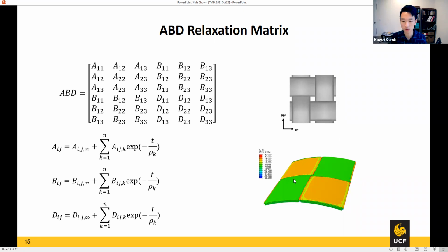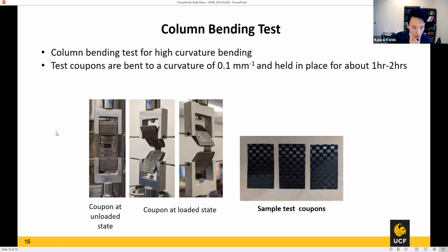So this is just a picture of what we actually have inside the simulation. This is a plain weave unit cell. There are 4 layers of thin ply composite to make up the total composite. In this particular case, we are trying to do a bending simulation to get the bending stiffness. D is the bending stiffness, A is the in-plane stretching, B is the coupling between bending and in-plane behavior. We carry out some testing. This is a methodology called the column bending test. It's been developed in the community mostly by a very nice man called Tom Murphy.